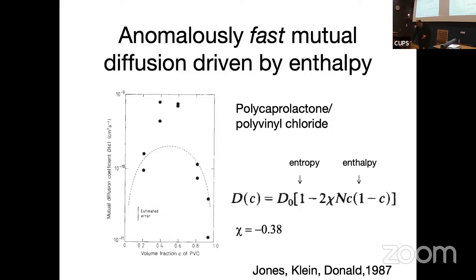Very fast diffusion can be driven by enthalpy. I put this in mostly because it's what I did in my PhD. Why this works for polymers is because there's a factor of N. Polymers don't like to mix because they're very big molecules, and so you don't get a lot of entropy when you mix them. So in those cases, even a very small degree of interaction from enthalpy can overcome that and make them want to mix faster.